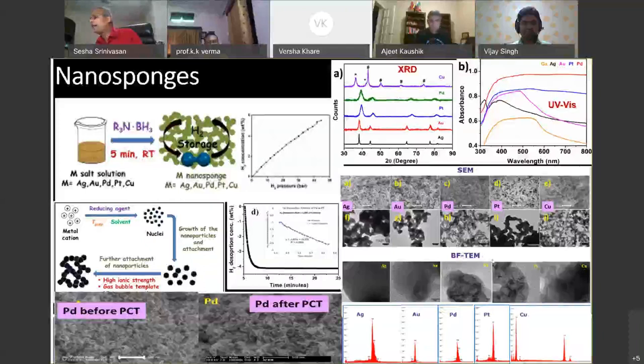TEM or HRTEM, we could see the nanoparticleization of this, and also you can see the very nice elemental composition of this. Overall, the goal for this material is to improve the kinetics and storage capacity of bulk palladium. A bulk palladium and a nano sponge palladium will behave differently, and you will see in the SEM picture before and after PCT that the nanocrystalline version has more capacity for storing hydrogen with fast kinetics. So that's one type of material that we developed.